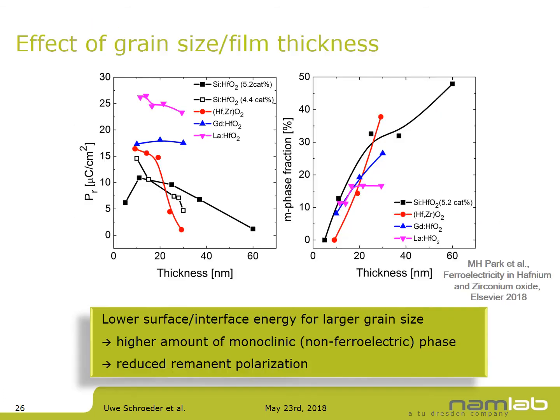The last root cause is surface energy, which is directly related to the grain radius of polycrystalline films. For very thin hafnium oxide films the remnant polarization is low; with increasing thickness it passes through a maximum before dropping again. This trend holds for different dopant materials. The key observation is that as thickness increases, the monoclinic phase fraction within the hafnium oxide layer increases, which is the main cause of the reduction in remnant polarization — directly related to the increasing grain size.